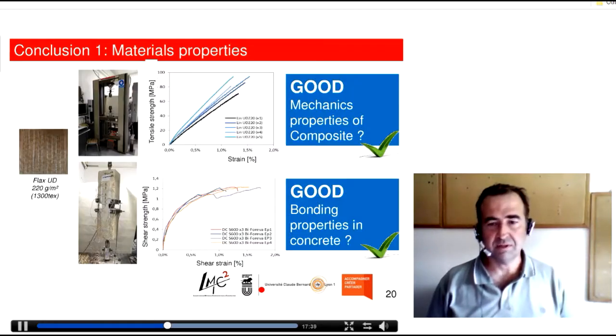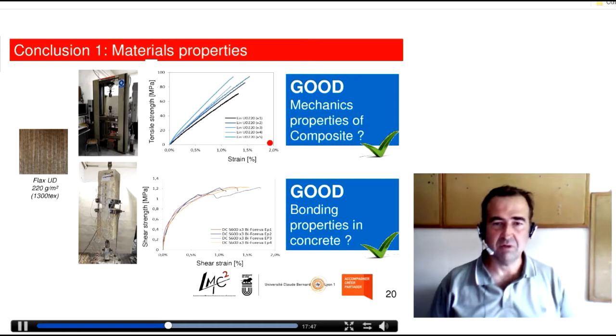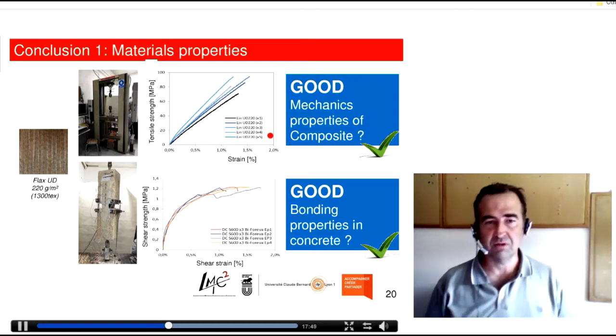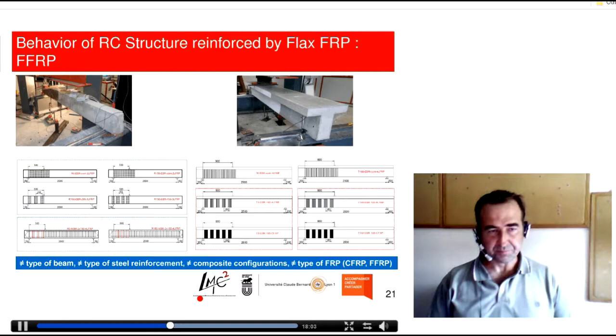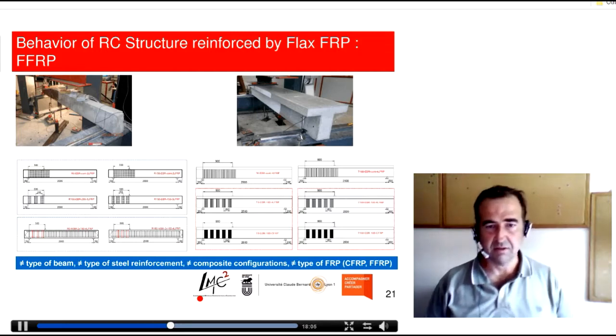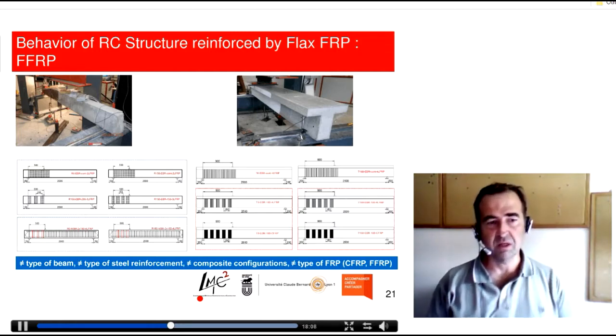So, to conclude this first introduction, what we can say is that the properties of flax fibers, if you develop them well, the composites may be very nice and comparable to the ones that we have with glass. That bond is not a real problem on concrete, and we can develop higher level of strength onto the concrete and low level of sliding, so the behavior may be very interesting. So next stage may be to do the tests at the scale level of the structure.